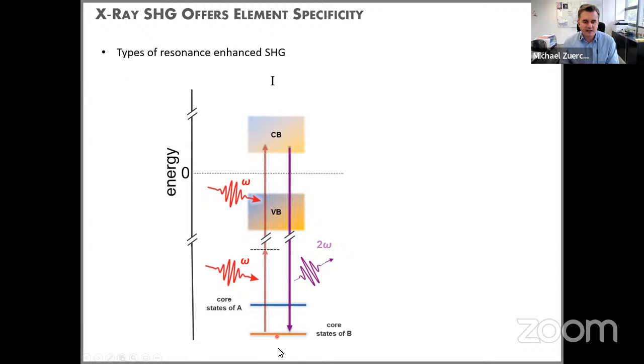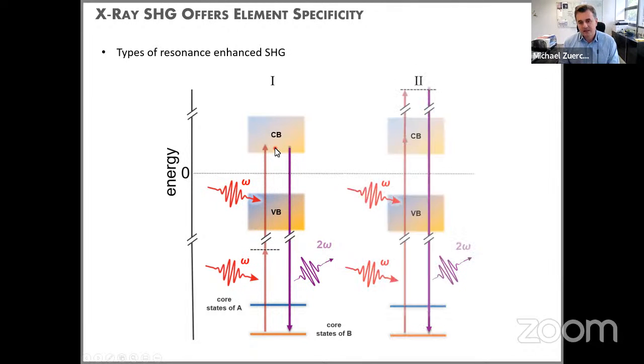We always have to create a resonance condition to take advantage of real existing states to cycle the electron through to actually observe second harmonic. So there is one possibility to basically go what we typically like to call half resonance. We use photons that have half the energy of the resonance from a core state to an empty conduction band state. Or we can also go the other way, where we use one photon to go resonant to a conduction state and then cycle through a virtual state at much higher energy and can observe second harmonic